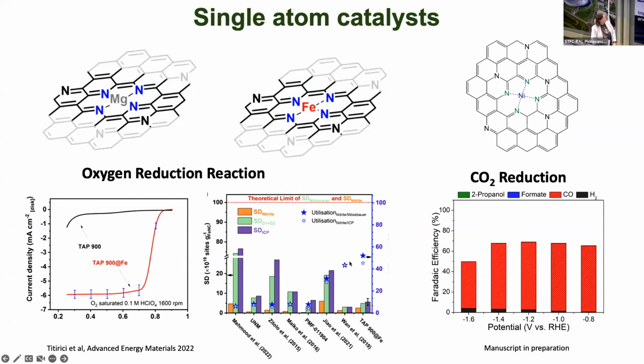And you can see here that this is our material, this TAP 900, that gets one of the highest, or the highest, active site utilization so far in the literature for this reaction, which is quite nice and impressive, because it's not only that you have a lot of these active sites, it's how many of them are actually active, and this is more important. Now, of course, there are still issues with this catalyst, in particular its stability. I think that's the next big challenge that we need to solve in order to make this catalyst a commercial reality for fuel cells, because they work quite decently, almost as good as platinum, but they're not very stable.